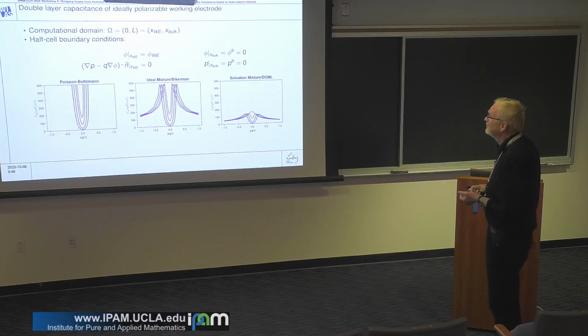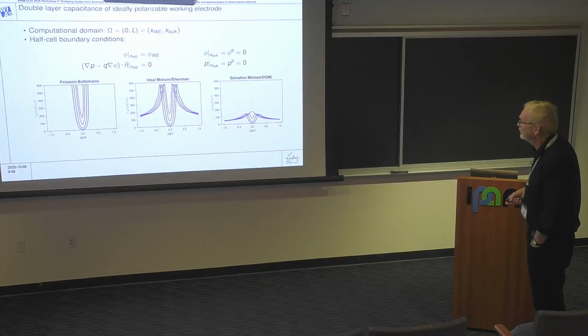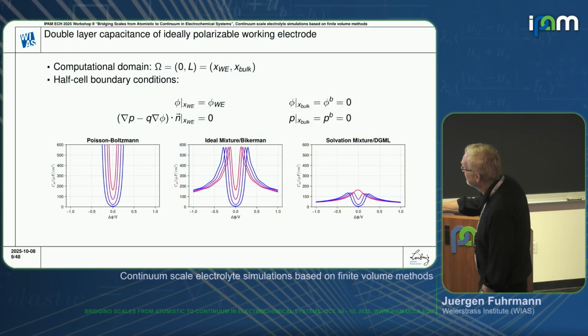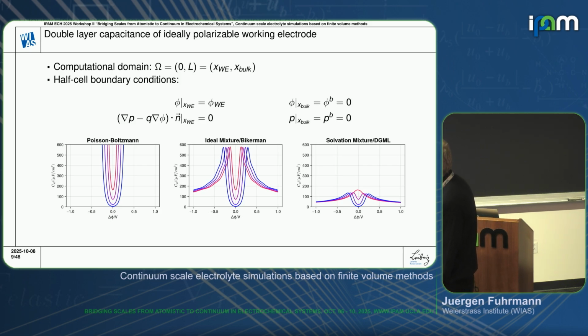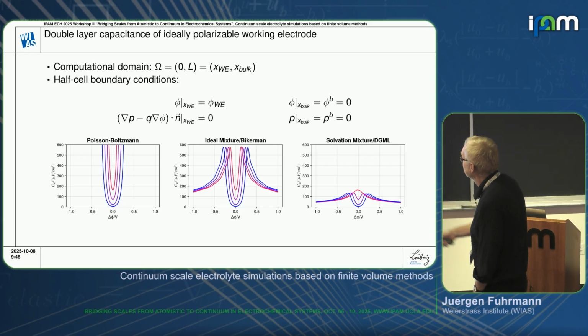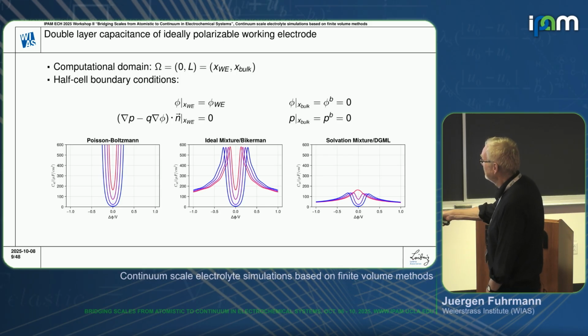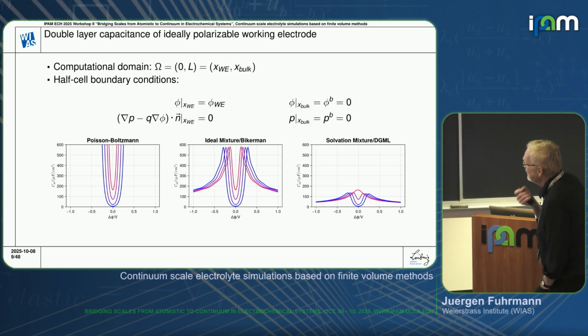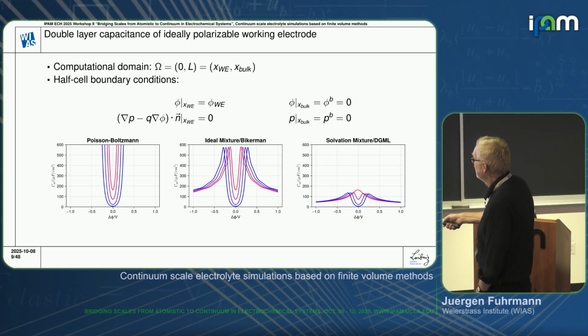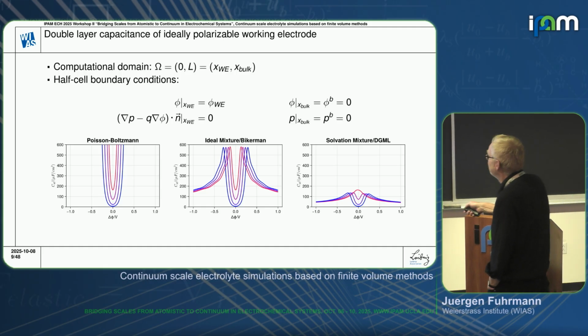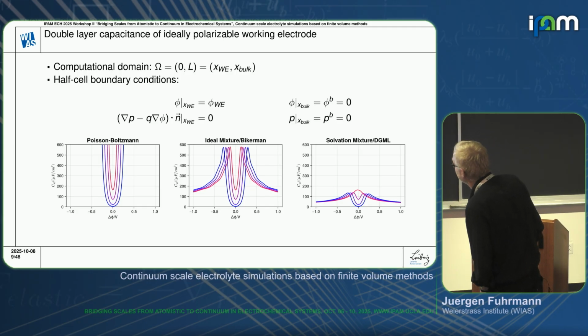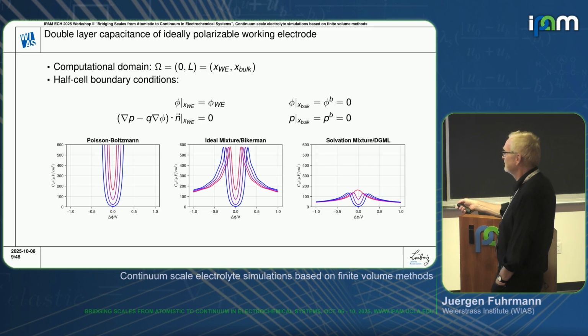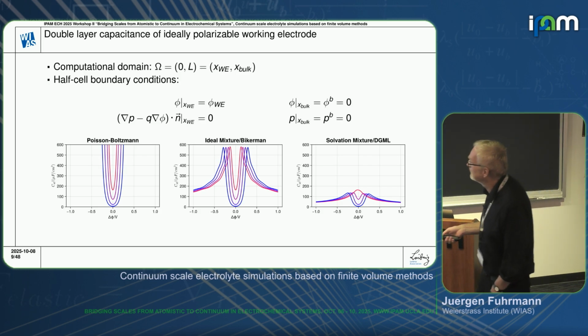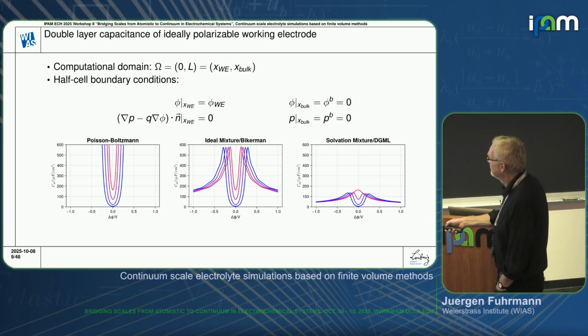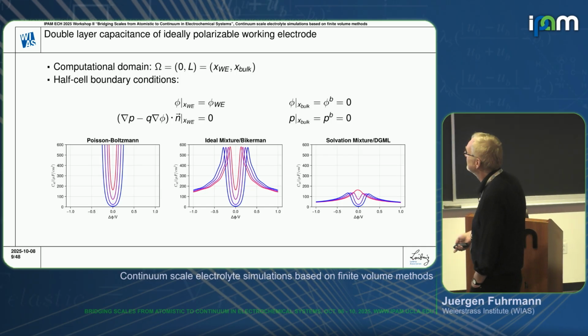And if we now set up a computational domain, which would mean some kind of double layer, some ideally polarizable working electrode, we can set the electrode side as a working electrode, apply a potential, and a no-flux boundary condition for the pressure, and some bulk boundary conditions. We get the Poisson-Boltzmann double layer capacitance curves. With the ideal mixture or the Bikerman model, we see this camel shape, and we can go down to realistic experimental values if we introduce the solvation mixture by the model of Dreyer, Guhlke, Müller, Landstorfer. So this was essentially what Manuel quite a bit talked about. Yeah? So the different colors in the curves give rise to different molar concentrations here.